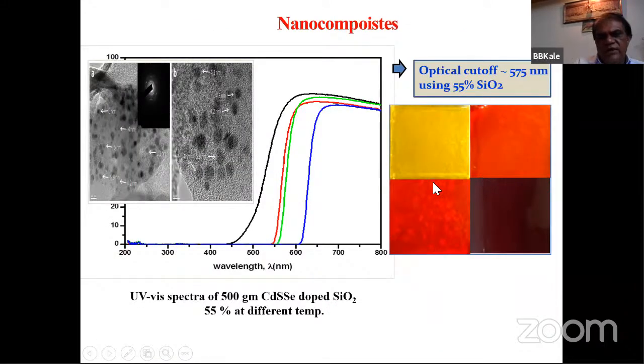Here you can see the different colors. It is a cadmium sulfide glass. It may be 2.5 nanometer, 3 nanometer, 4 nanometer, 5 nanometer. So with quantum dots, it changes the color. Accordingly, absorption also changes. So you see, quantum dots are size sensitive.